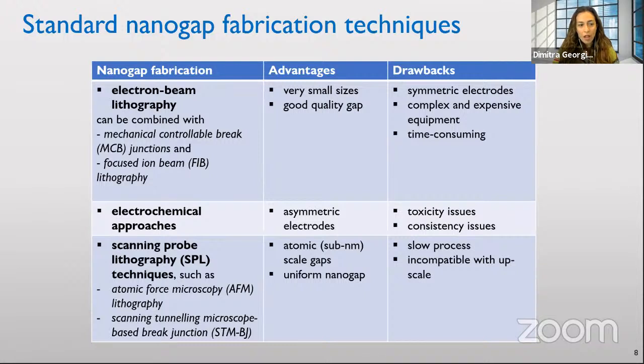device. Then we can use scanning probe lithography techniques such as atomic force microscope lithography or scanning tunneling microscope based break junction techniques. Actually, with these techniques, one can get ultra short gaps, atomic scale gaps in the sub-nanometer range, and very uniform ones. Again, this is a slow process. It's not yet scalable, and that's why it's mainly used for research purposes.